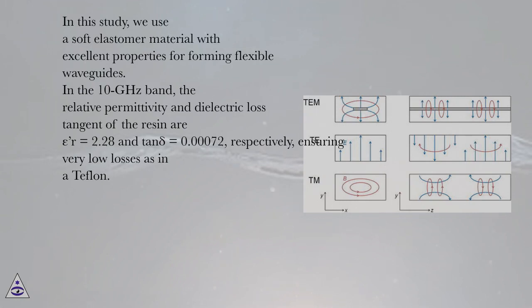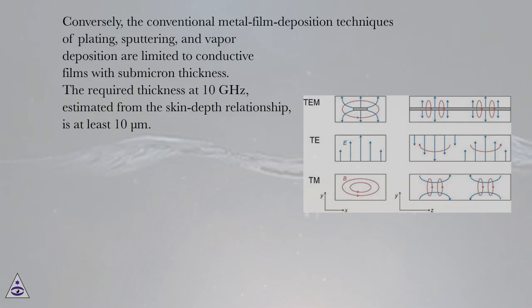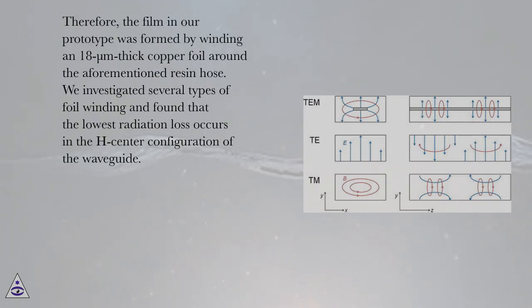In this study, we use a soft elastomer material with excellent properties for forming flexible waveguides. In the 10 GHz band, the relative permittivity and dielectric loss tangent of the resin are epsilon R equals 2.28 and tan delta equals 0.00072, respectively, ensuring very low losses as in Teflon. Conversely, the conventional metal film deposition techniques of plating, sputtering, and vapor deposition are limited to conductive films with submicron thickness. The required thickness at 10 GHz, estimated from the skin depth relationship, is at least 10 μm. Therefore, the film in our prototype was formed by winding an 18-μm-thick copper foil around the aforementioned resin hose.